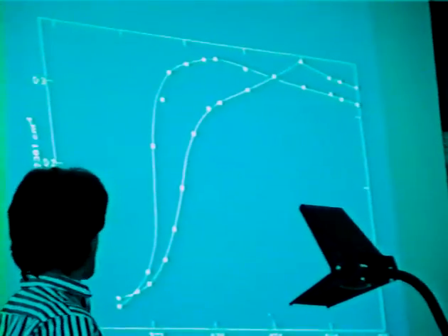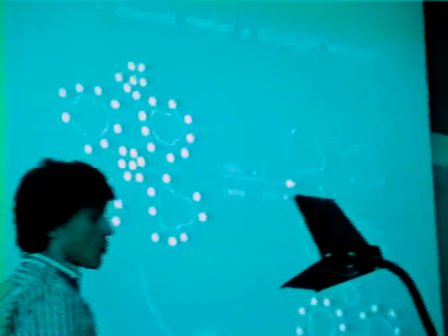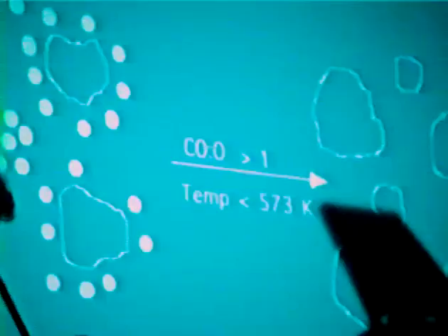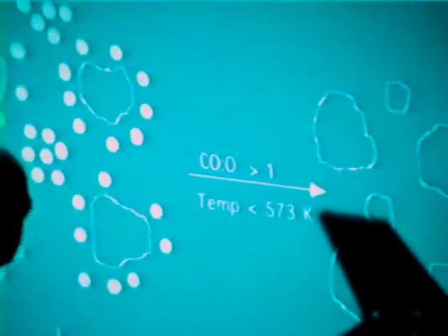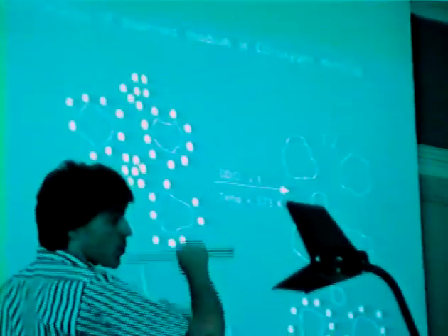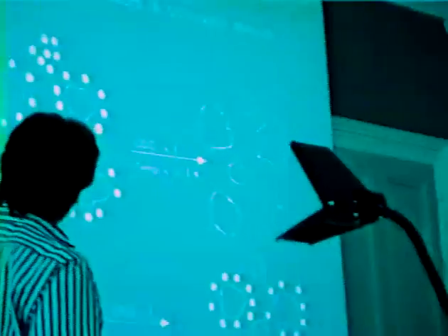So essentially, there is some modification to the rhodium crystalline surface. Can I get the next slide? I can represent this as follows. We look at the white dots here, which represent the gem dicarbonyl sites, and then we have these small crystallites, in which initially CO is adsorbed on rhodium in the bridge mode. So we have loosely packed rhodium crystallites, which we saw both in the form of the twin peak maxima and due to the fact that CO is adsorbed in the bridging mode.